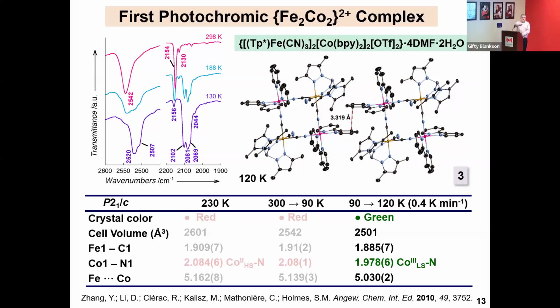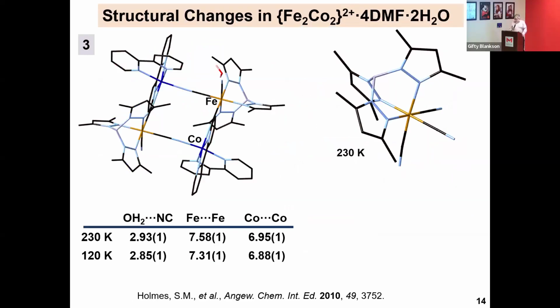And so you can clearly see that you get a contraction of the cobalt-nitrogen distance, likewise the unit cell volume. We get the color change that we all expect. All right, to show you in more detail what's going on, focusing at two different temperatures, we have hydrogen-bonded cyanide here. We still have one. We've removed the other one by putting that DMF into the lattice. Iron-iron contacts and cobalt-cobalt contacts show you that the clusters are well separated.